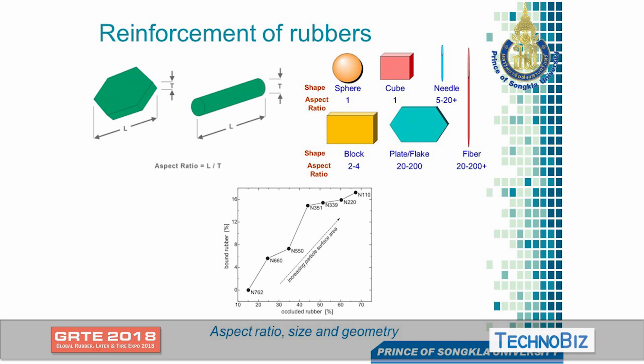So this is the example of the bound rubber content. Once we reduce the size of fillers used in the rubber or polymer matrix, it can increase the bound rubber content. So here is the example. We prefer as small as possible and as high an aspect ratio as possible to make the polymer matrix stronger.